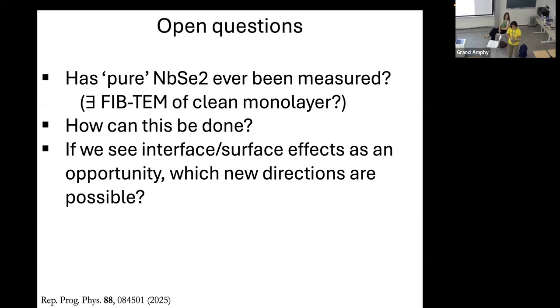Yeah, no. The problem with epitaxial layers is that when you go to 2, 3, 4 layers, the crystalline quality of the system gets worse and worse. So, particularly, I fully trust the monolayer, but not the second layer. For example, if you try to look at the charge density wave from the tri-layer, in the uppermost layer, you don't see the charge density wave. So probably it's not good enough. So you say that as a data point for a monolayer, the epitaxial is a good reference system. But if one wants to do thickness dependence, then you start running into practical problems with the quality of the growth.